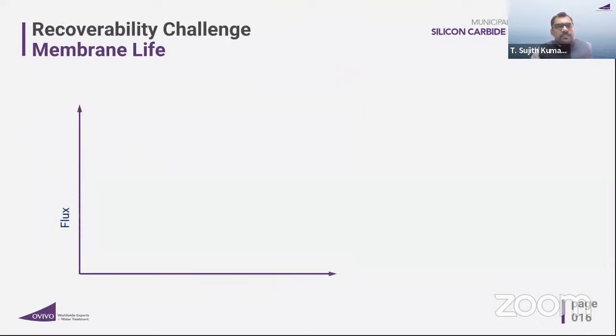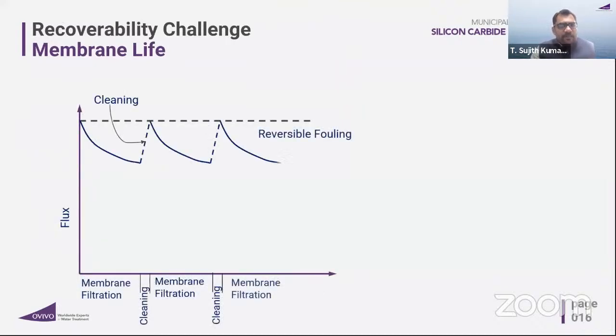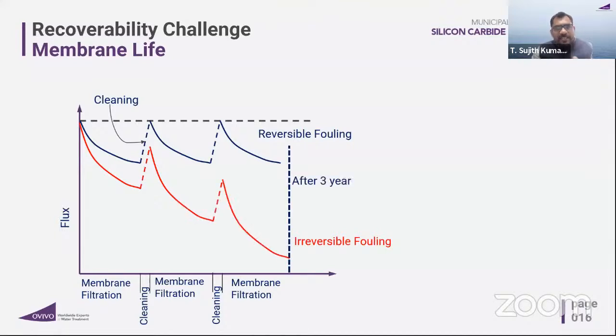The other recoverability challenge is the membrane life, right? When the membrane is new, as I said, any membrane is bound to foul and bound to scale. You'll see that you operate the system, right? Membrane will get fouled. You clean, the membrane will come back to the original condition, and you keep on using it. But after some time, you'll see there is an irreversible fouling happening, right? Once the membrane is cleaned, you'll see there's a flux decline. You're not getting back to the original position.